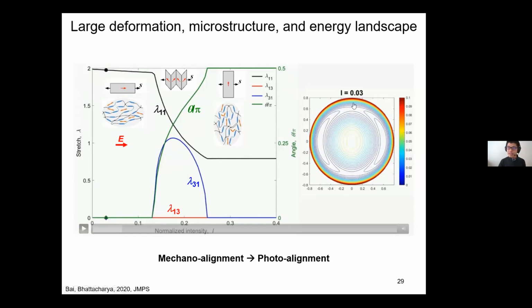On the right hand side, this is the energy landscape, the free energy landscape. So it's a polar coordinate system. The color is the energy, which doesn't matter too much, but the radial coordinate is the order parameter, whereas the angular coordinate is the angle between the polarization and the stress. Initially, because I have a horizontal stress, I have a global minimum here at a finite order parameter. They're ordered. The mesogens are aligned with the stress.